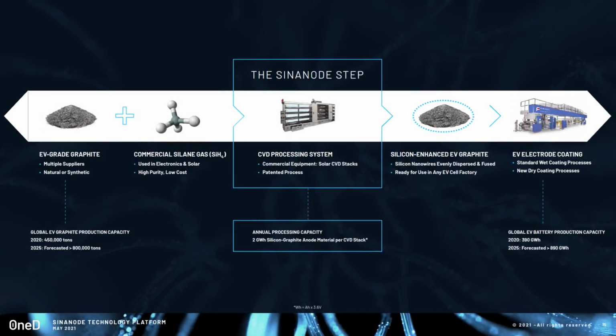Now, a catalyst, why is that so important? First, you need a cheap catalyst. Second, you need to make it in very large quantities where all the copper oxide nanoparticles are the same size, because that's what's going to determine the diameter of the nanowires. And we can do that at room temperature in a continuous process that is extremely cheap. But then when you mix it with graphite, the catalysts end up on the graphite particles, okay? And when you put it in the processing tube to react with silane, 99.9% of the silane is transformed from the silane gas into silicon nanowires. There are virtually no traces of silane in the exhaust. So you don't want to waste silane. You want to use all of it to make the nanowires because that's the only thing that counts at the end, okay? So that's the first part of it.